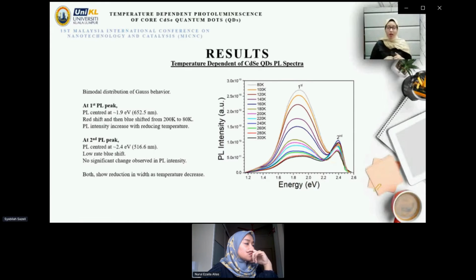For the first PL peak, as temperature decreases from 300K to 200K, a redshift of PL peak position is observed. Then it is blue shifted when the temperature decreases from 200K to 80K. PL intensity for each spectrum reduces with increasing temperature from 80K to 300K. For the second PL peak, a blue shift is observed, but only at a low rate, and no significant change is observed in the PL intensity for each spectrum.